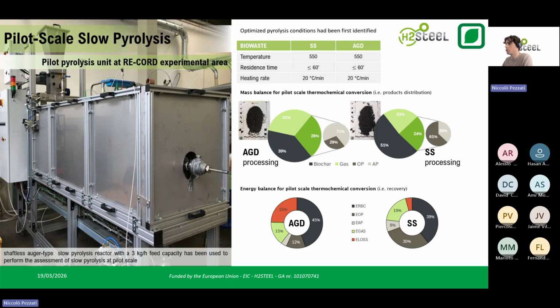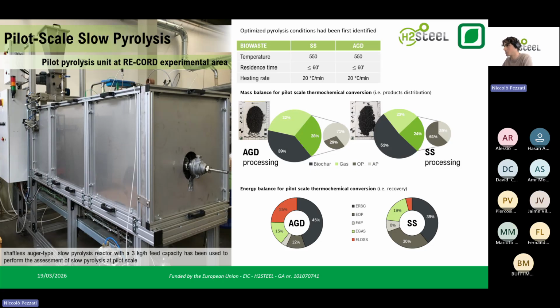So we have converted both the biowaste streams at 550 degrees Celsius with a residence time in the conversion chamber not exceeding 1 hour, and fixed heating rates of 20 degrees Celsius per minute, which is typical for slow pyrolysis processes.